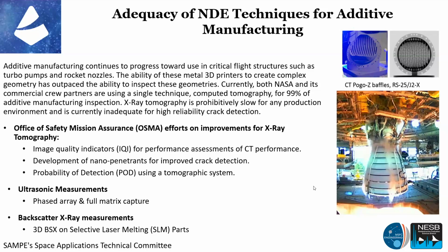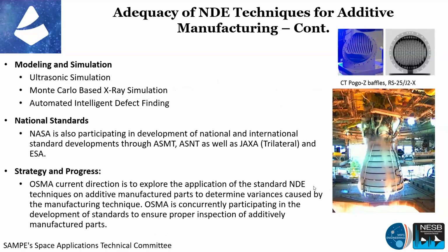We certainly looked at a lot for ultrasonics and found more issues than solutions, both for the most popular phased array and full matrix capture. And again, we've been working on backscatter X-ray, the 3D X-ray for laser metal parts, which has shown some good results. Definitely put a lot of work into modeling and simulation, especially for these really complex parts. So can we make a simulation on a complex part so that we know where to put the sound in effectively to get a signal from a defect in a certain area of the part? And I'm going to talk a lot about that too.